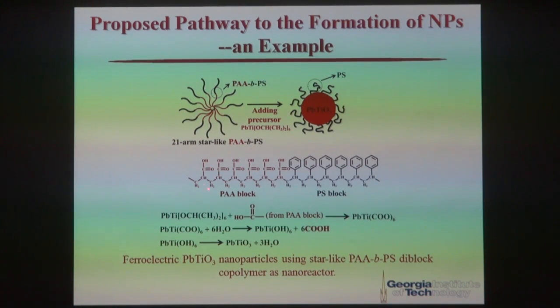First of all, we have this PAA block connected with PS block. So this PAA block has carboxylic acid group, negatively charged. And this negatively charged species can react with the metal moieties in your precursor. So lead 2+ and titanium 4+ can react with this carboxylic acid group, forming intermediate compound. So this intermediate compound hydrolyzed a little bit and forming another intermediate compound. Finally, we do the condensation reaction, reflux reaction at the elevated temperature, eventually leading to the formation of that titanate nanoparticle. So this is what we proposed, the reaction going on.